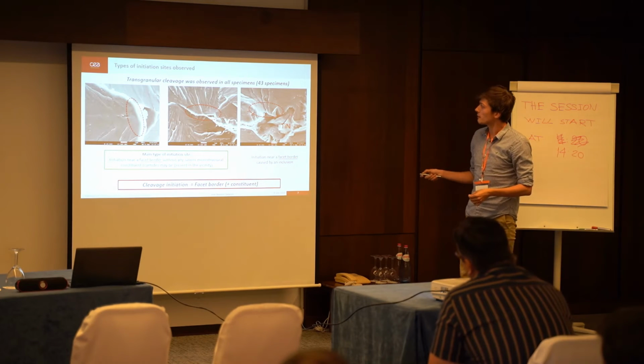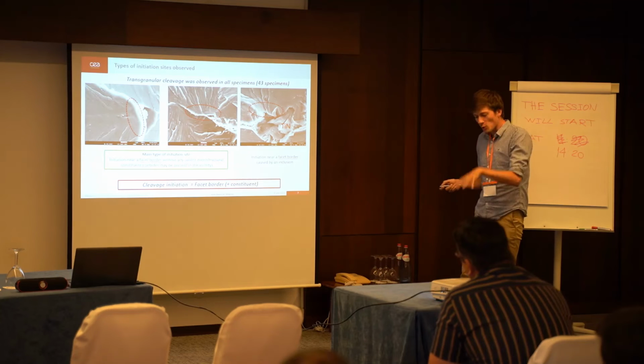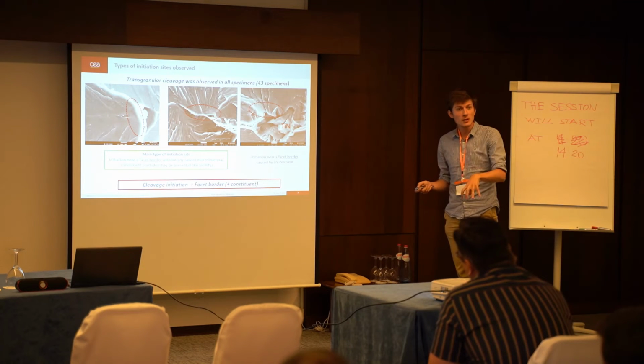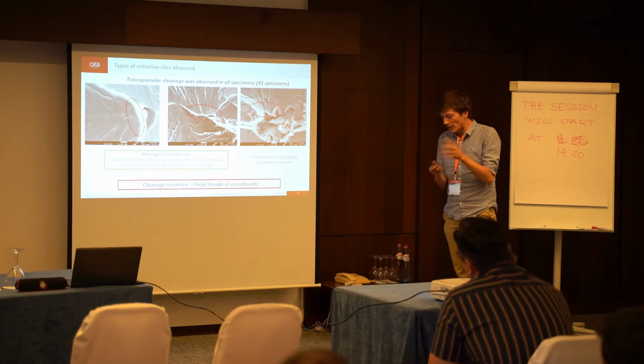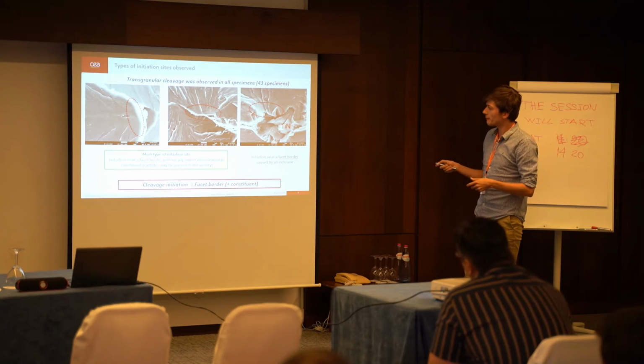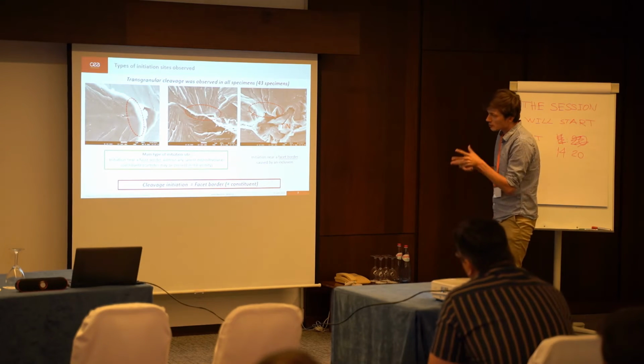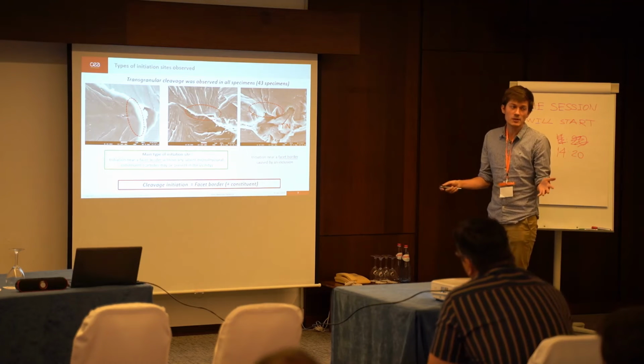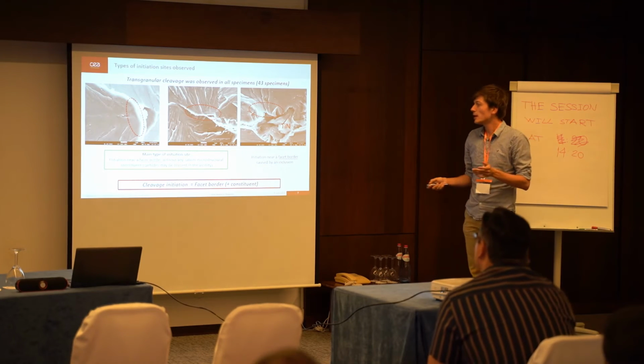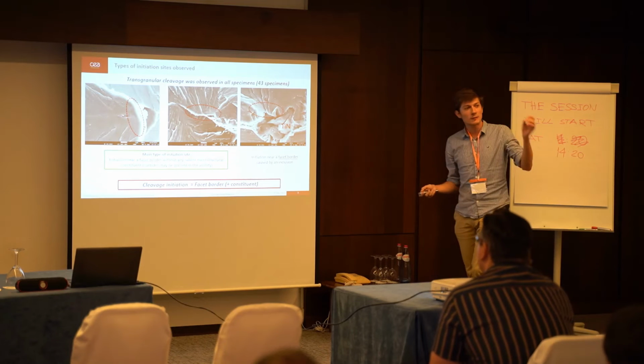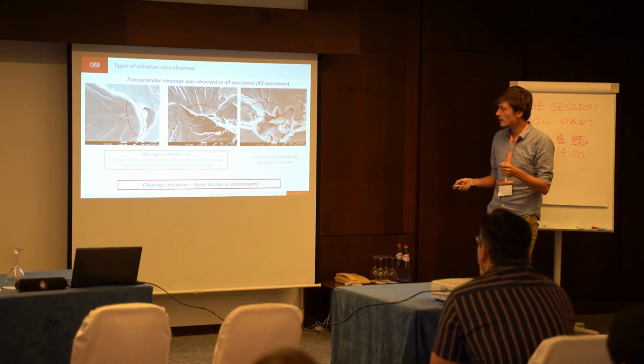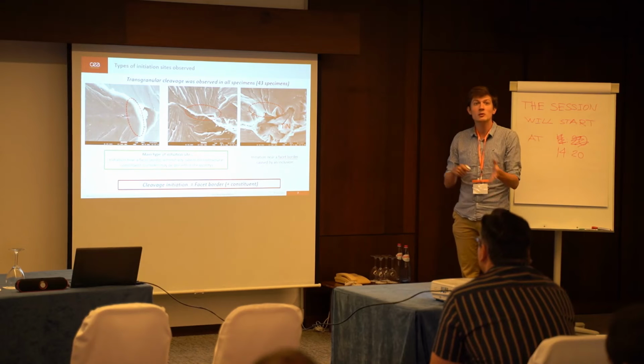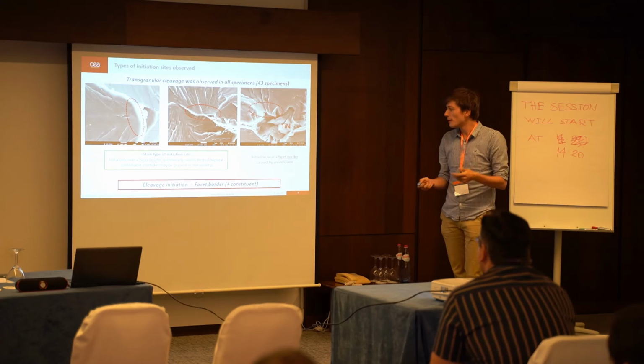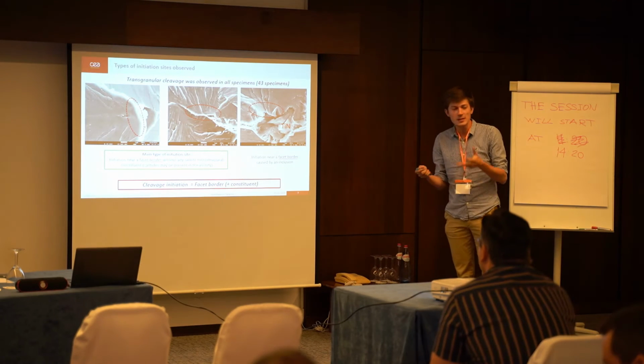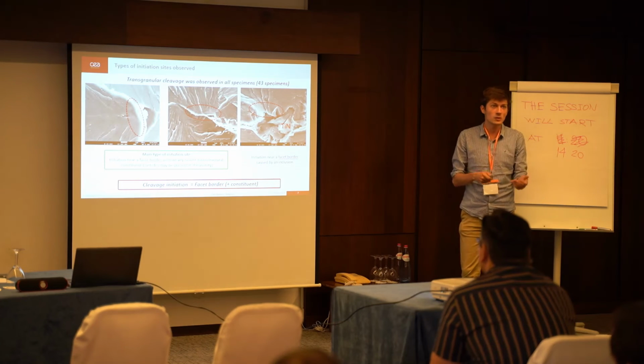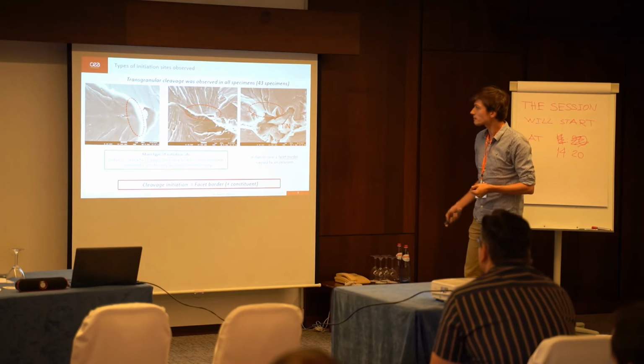And finally, for the picture on the right, you are always at the facet border, but there were some inclusions that broke and caused the initiation of brittle fracture. So to summarize, for all our specimens, for all the materials considered, cleavage initiation always happens at the facet border, a microstructural boundary, with sometimes some constituents that could maybe modify the behavior, but those constituents do not seem to be necessary to the initiation of brittle fracture.